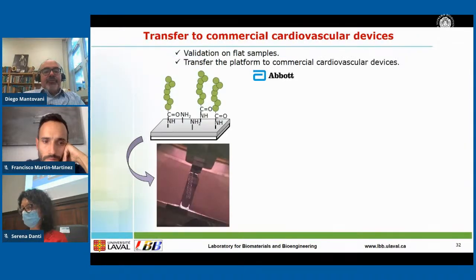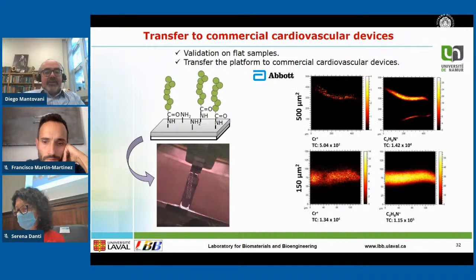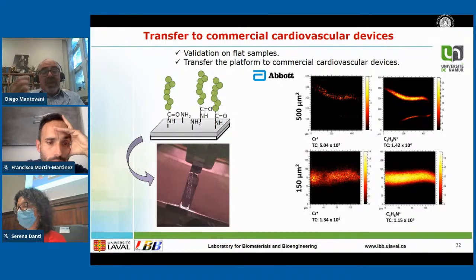And then we transferred this to a commercial cardiovascular device. So 80 micron stents were provided by Abbott, which was a good partner in this project, and then it started to become a bit complexified, because what I presented to you up to now was done mainly on flat surfaces. All the processes were optimized on flat surfaces. And now you have in your hands an 80 micron structure stent, 3 centimeters long and 3 millimeters in diameter, and when expanded it is maybe 3.5, so 1.7 to 3.5. So a very tiny device, very complicated to manipulate.